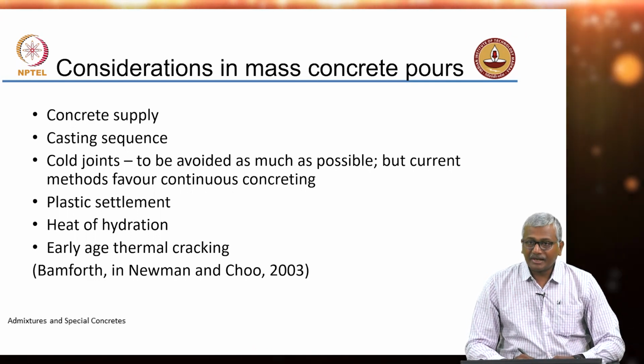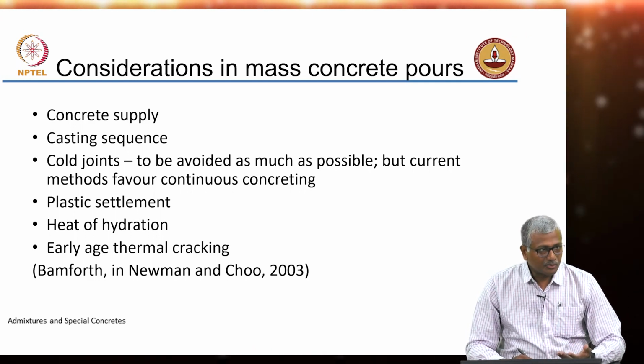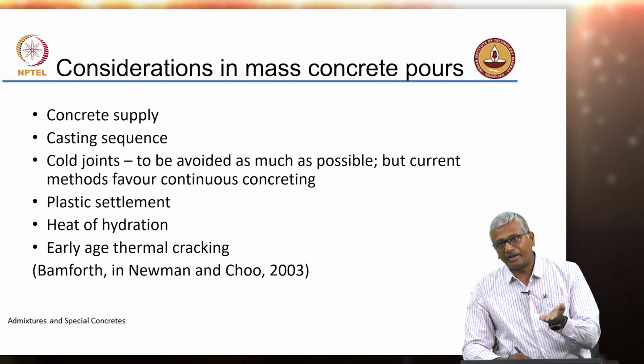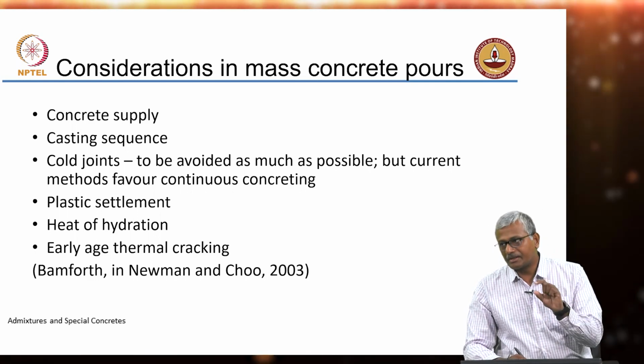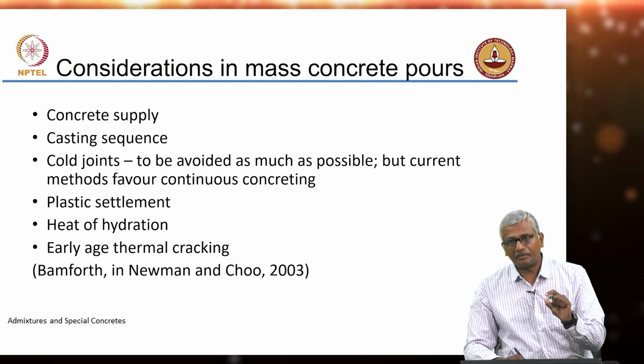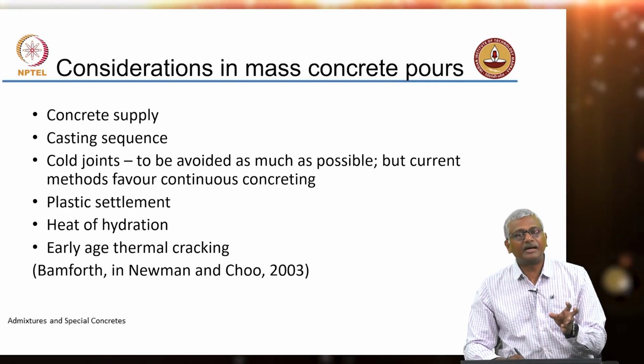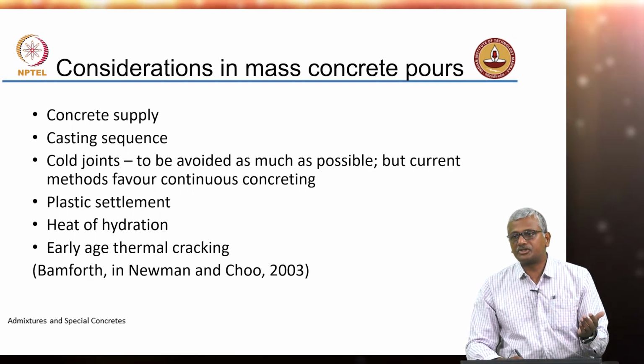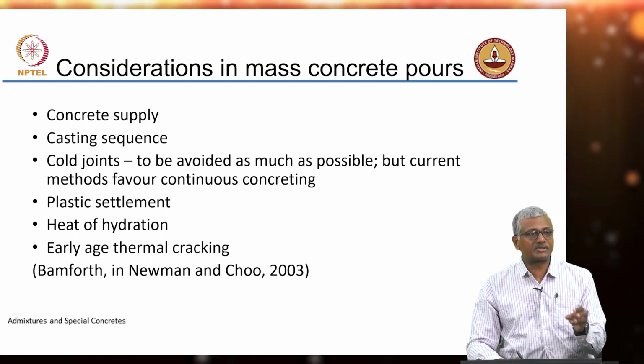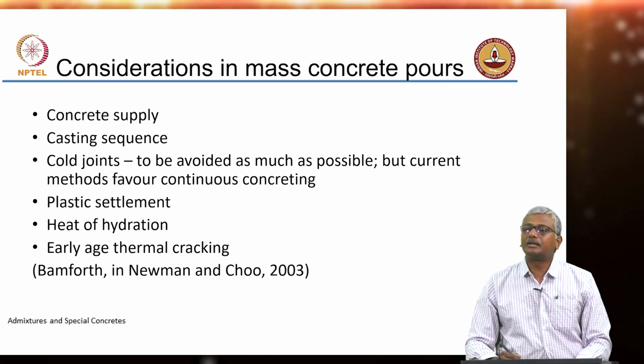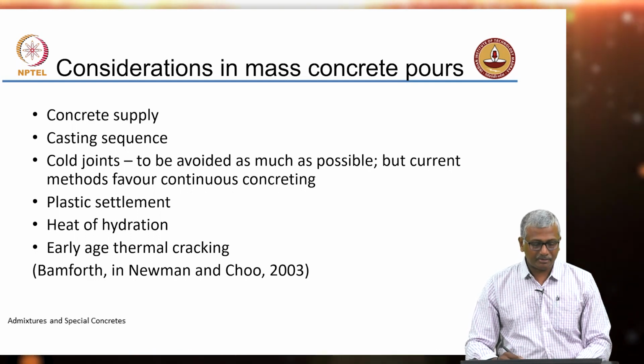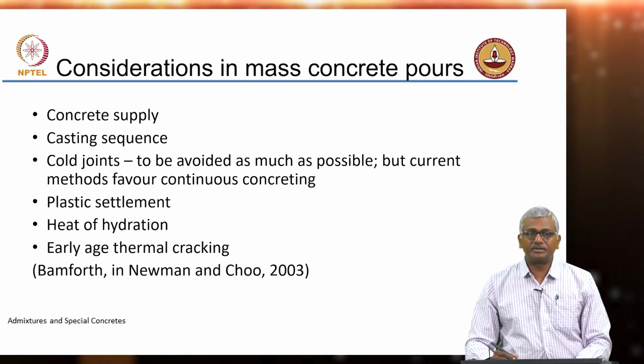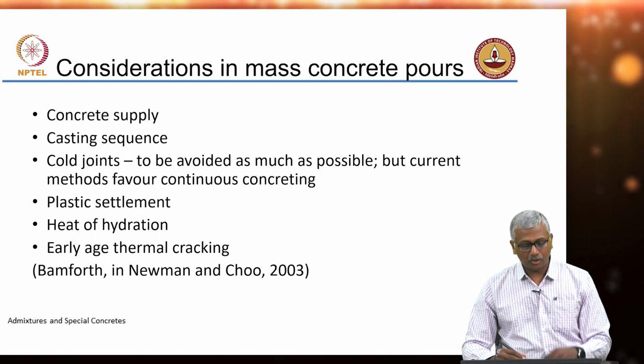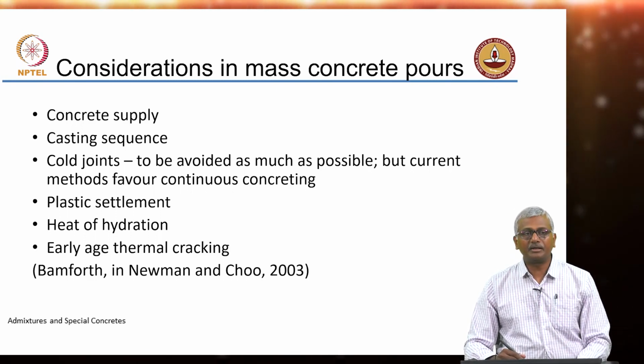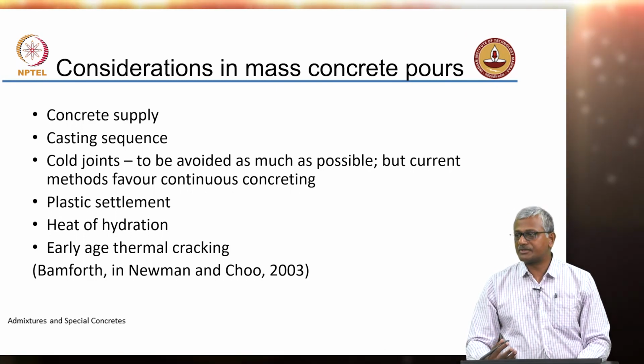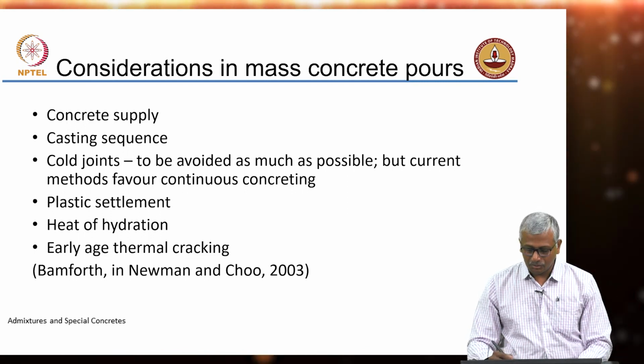One problem that can arise is plastic settlement also, because again we talked about the fact that your top cover is not adequately measured, and because of which, if your concrete has a high degree of flow, there is a substantial opportunity for the aggregates to subside, causing a cracking right above the rebar. That is called plastic settlement cracking. Heat of hydration is obviously the main consideration, which we will talk about, and early age thermal cracking arising because of this heat of hydration is the other thing that we need to look at.